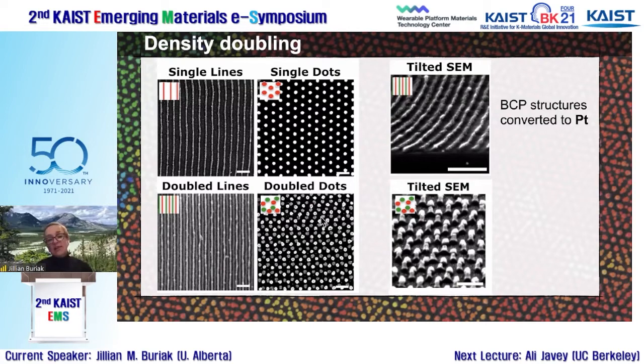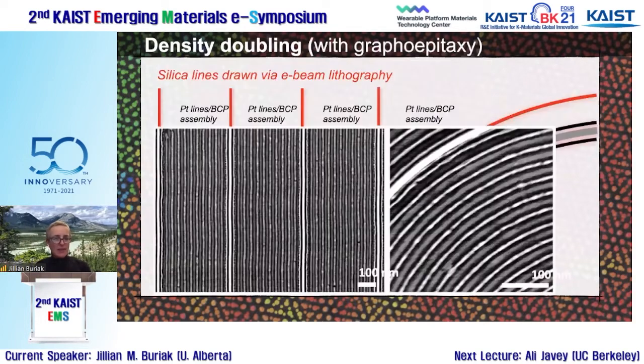It seems to also work with dots. And when you look at the tilted SEM in the top right-hand corner, you can again see that bright, dim pattern. And what that's due to, you can see in the AFM imaging that we did in this paper, is that the bright, dim is simply an artifact of the electron microscopy imaging. So the bright ones are very tall, and those ones are derived from the top layer. And then the ones at the bottom are flat, and those are the ones derived from the bottom layer. So it's taller, wider, and flatter. So it's not a perfect way to hack it and to decrease the spacing.